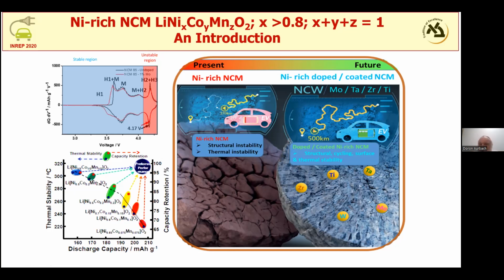Now, as we increase the amount of nickel, and we can go even up to 100% nickel, coming to lithium nickelate, then we increase the specific capacity. But we also increase the instability. So if you look, when we increase the amount of nickel, we can increase the driving distance because we have more specific capacity and more energy. But the particles are cracking, they are stressed, and we have unstable morphology of the particles.